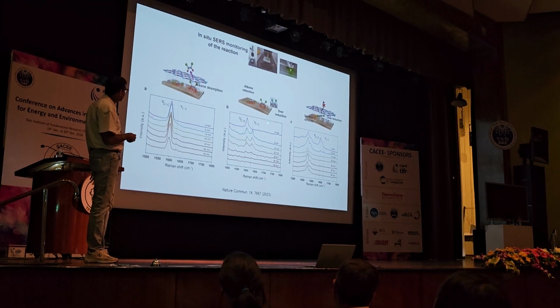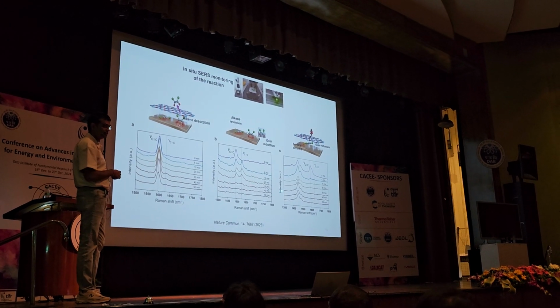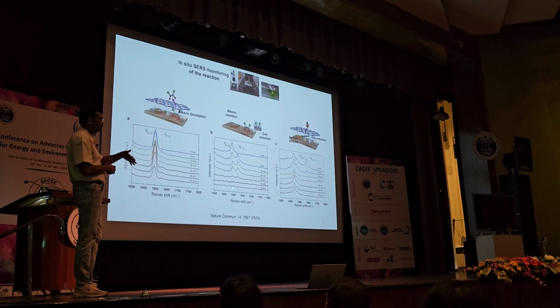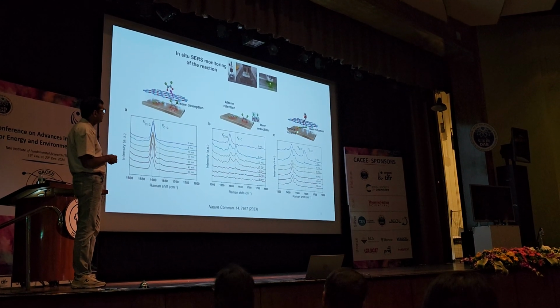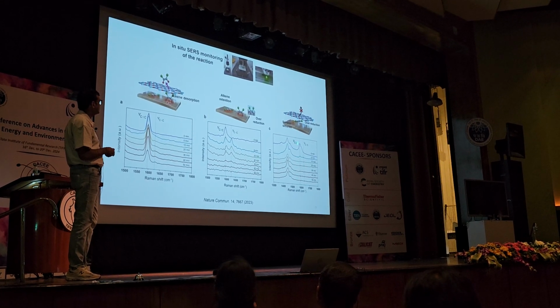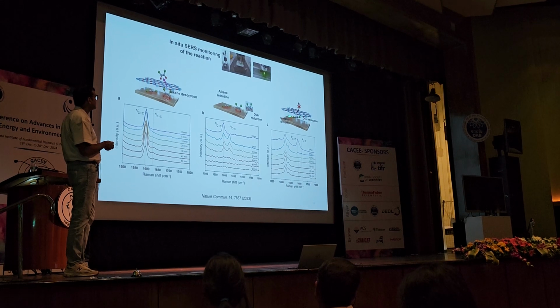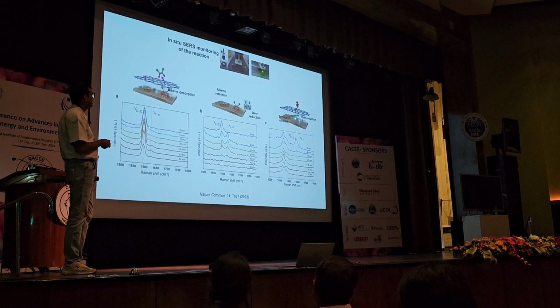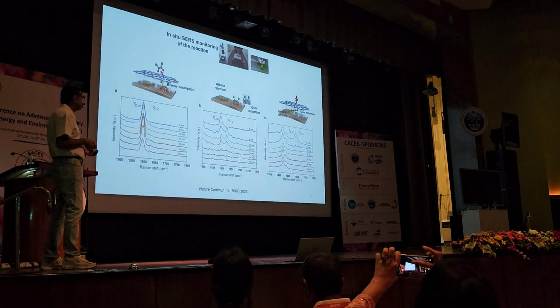In the second case, we remove the PCOL and we see that alkene exists, which is responsible for its over-hydrogenation. In the third case, we intentionally bound the alkene on the catalyst surface and found that it gets over-hydrogenated even in the presence of PCOL, because now this substrate doesn't have the facility to fly off from the catalyst surface.